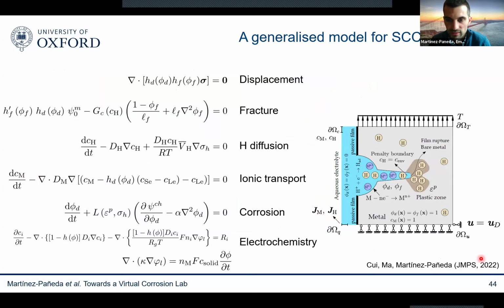So stress corrosion cracking, again, is a very complicated problem. It's because not only do you have anodic dissolution, material detachment, but you also have fracture that is originating due to mechanical rupture, but typically accelerated due to the ingress of species such as hydrogen. So it's a complicated problem, and you need to make an assumption before you model on what is the dominant mechanism. But the good thing about these models and computers being big enough is that we don't need to make any assumptions. We can simulate everything into the model. We can become greedy. We can add all the ingredients and let the model decide for us.